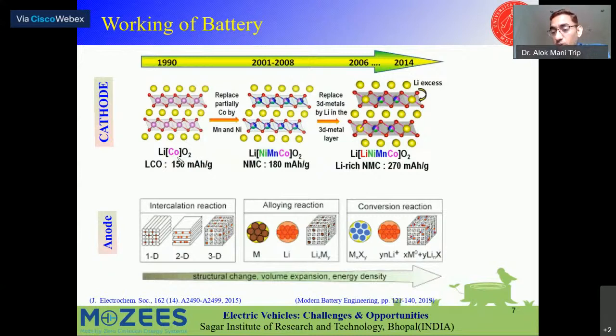The lithium cobalt system has the problem that in the first cycle itself, we are losing 50% of the cobalt from the lattice. I'll not go into detail how it is happening, but they have used nickel and manganese with the cobalt, and finally the system got stabilized. And with that, since they have used nickel, the potential has gone up. And when the potential has gone up, the capacity has increased. And then they have several compositions of this nickel manganese cobalt.